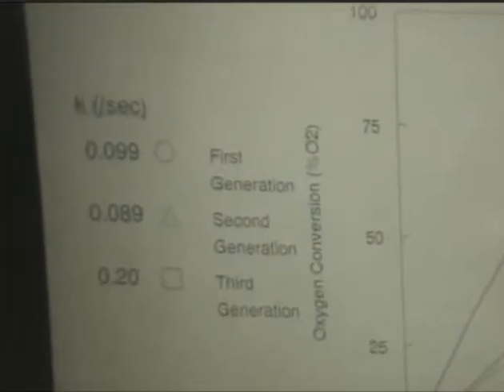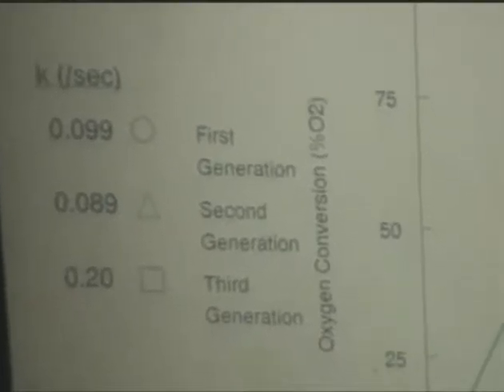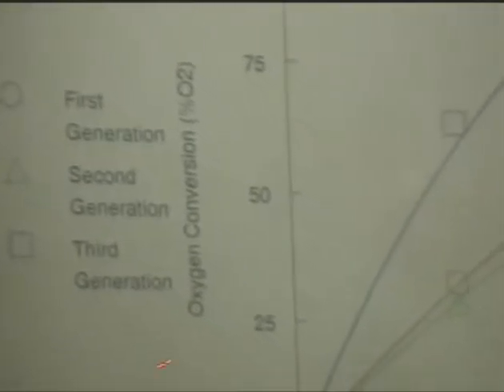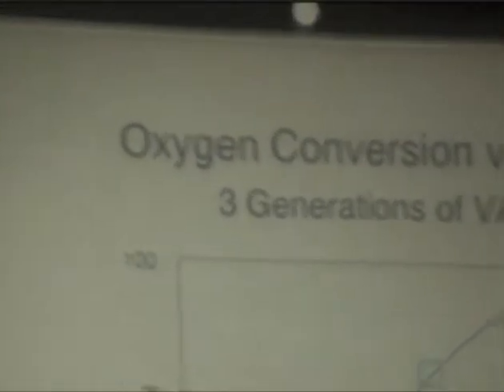So we scaled that up, at least to the big 100-gram size, and we see that, again, comparing our first generation, second generation, and now what we would call our third generation catalyst, that this catalyst does indeed, at these 100-gram levels, have a higher activity than do the prior two generations.